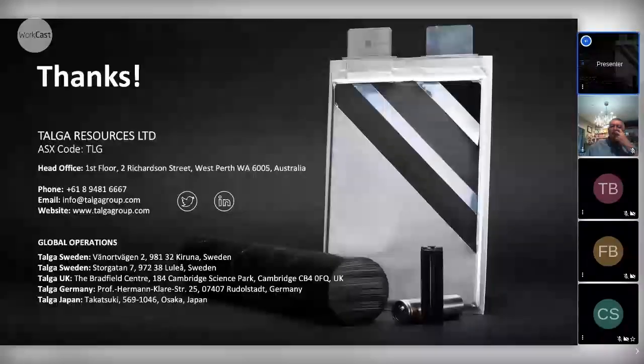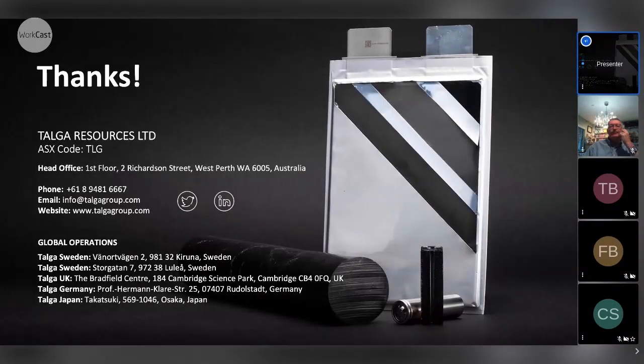So that was it. Trying to just be short and sweet on just probably a relatively little known use of graphene deep in the heart of batteries, which, to be honest, even today, silicon, as I said, is getting used more and more in anodes, but it's topping out at about 3 to 5% because of these problems.